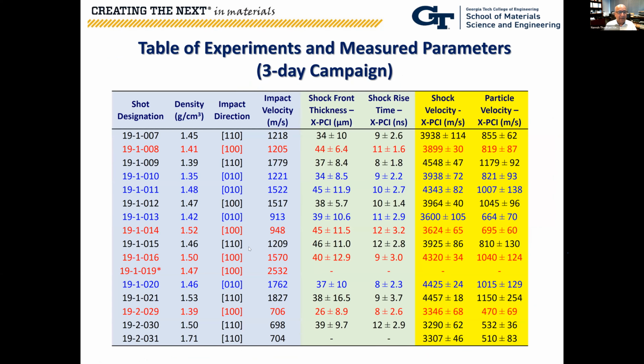If we do that, this gives you the table of all of the experiments that we did. This was a 3-day campaign, about 19 experiments. The different color codes indicating in the lettering are the different orientations - for example, the 110 impact direction, the 100 impact direction, or the 010 impact direction - for the impact velocity of each of the experiments.